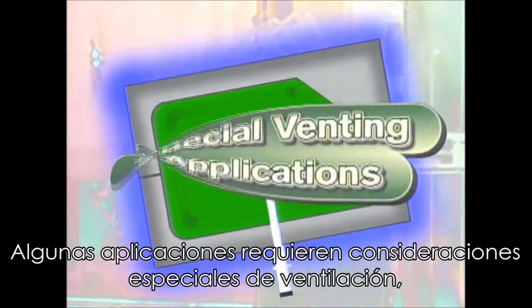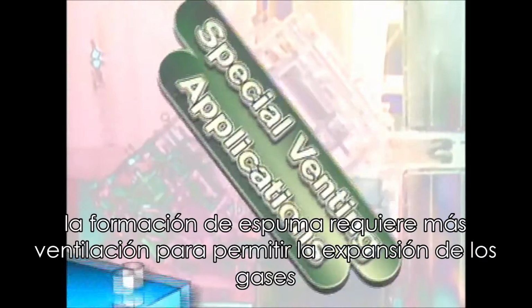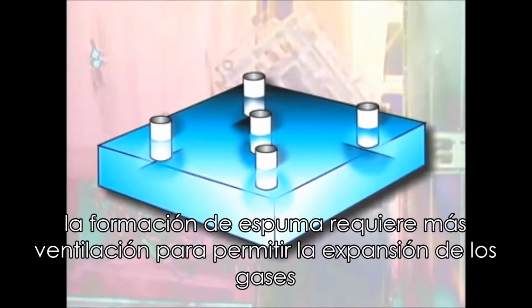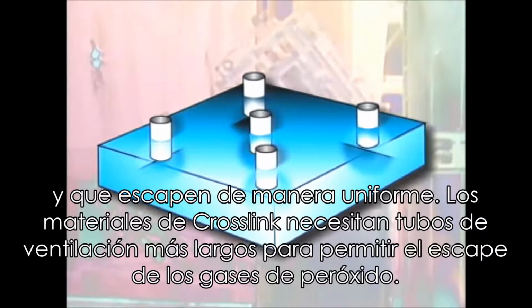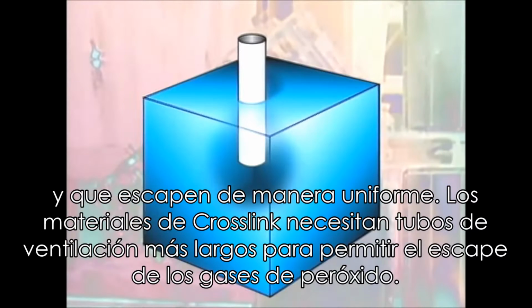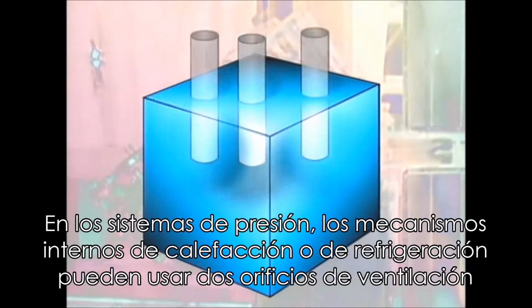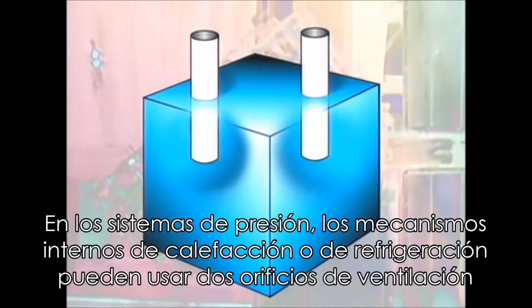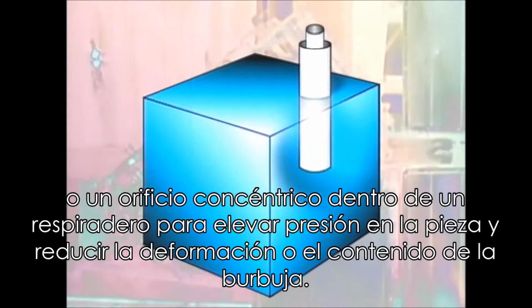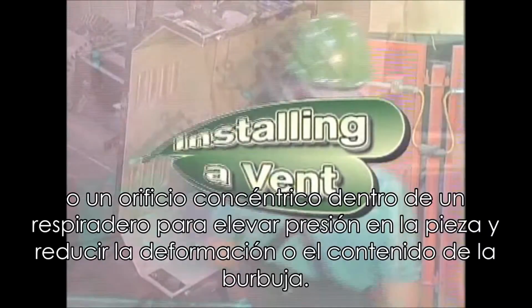Some applications require special venting considerations. Foaming applications will require more venting to allow expanding gases to escape uniformly. Crosslink materials need larger vents to allow peroxide gases to escape. Pressure systems, internal heating, or cooling mechanisms may use two vents or a concentric vent within a vent to raise pressure in the part and reduce warpage or bubble content.